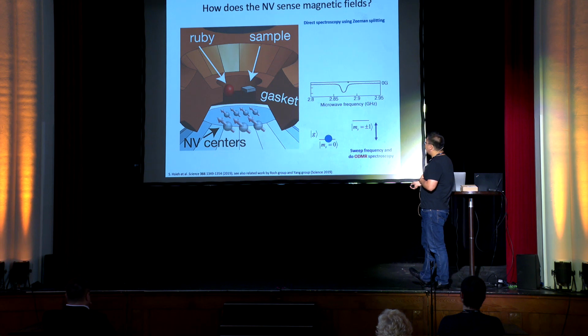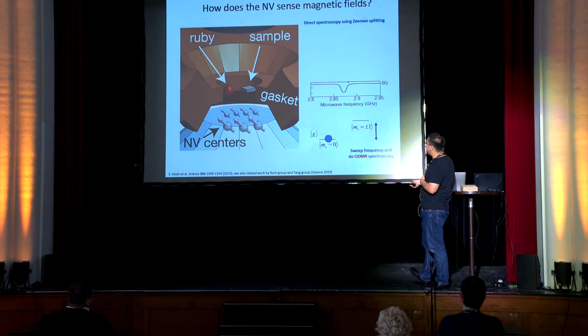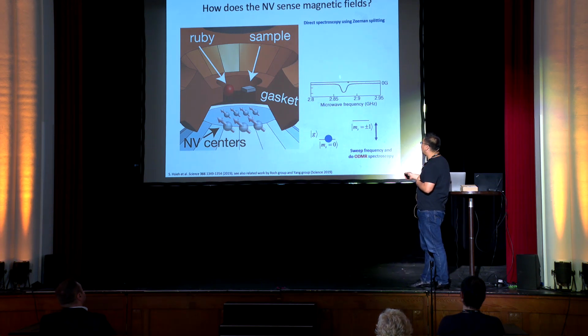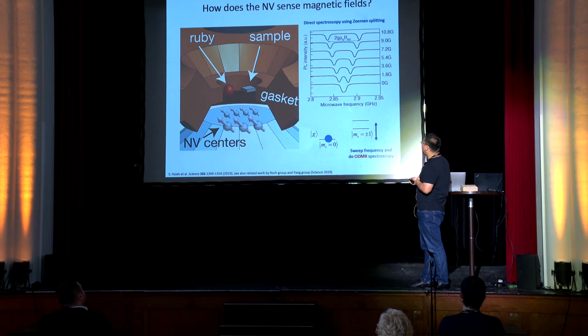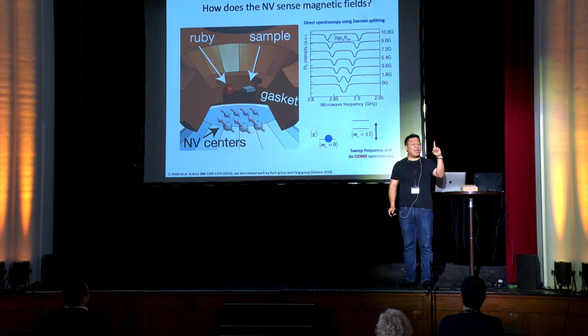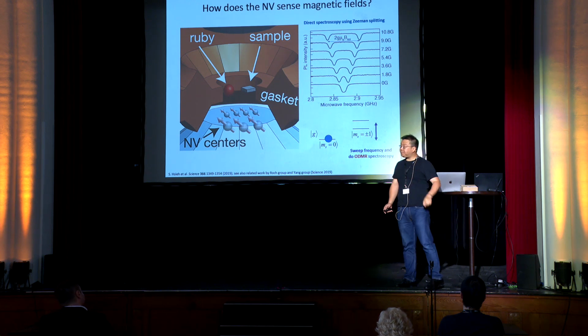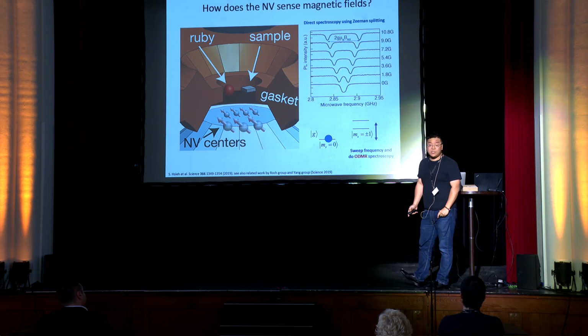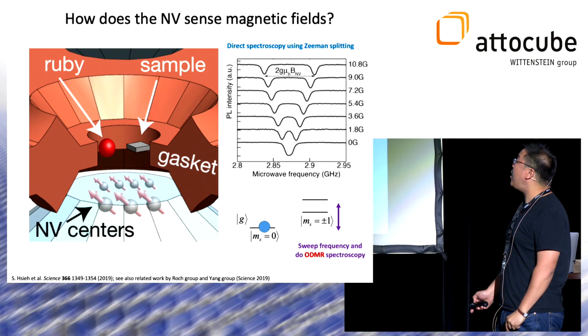Good. So the signals that you'll see in this talk are actually extremely simple. As I mentioned, it's a spin 1 dipole. So at zero magnetic field, the transitions between the m_s = 0 and plus or minus 1 states are degenerate and happen at a particular microwave frequency, about 2.87 gigahertz. As a function of increasing magnetic field, there's a Zeeman splitting of the plus and minus 1 states, proportional to the Bohr magneton. That splitting immediately allows you to back out the projection of the magnetic field along the nitrogen vacancy axis.